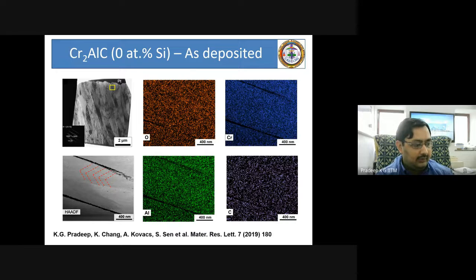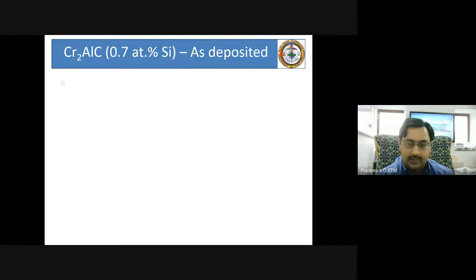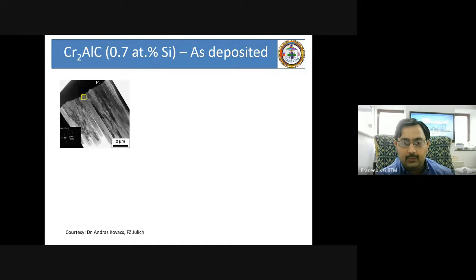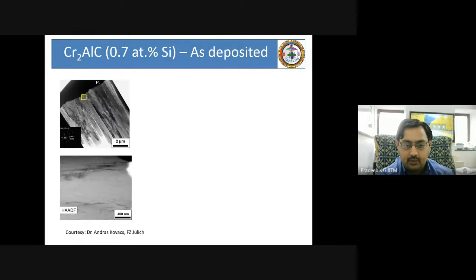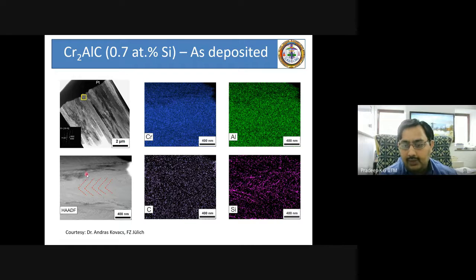We did the same thing with the 0.7% silicon added material. We see the same columnar grains. We zoom into this particular region to see the microstructure in the zoomed-in state, and the same uncharacteristic V-shaped defects are visible, which are a consequence of thin film growth at the nanoscale. Then when you do the chemical mapping, you suddenly see the presence of silicon in the form of a V-shaped geometry. That means silicon forms a V-shaped structure, or enrichment along the V-shaped region, which coincides with this particular V-shaped defect.